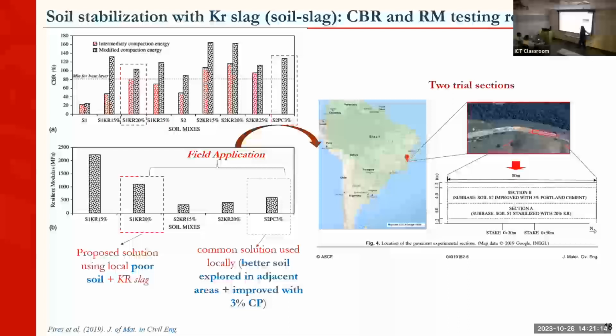We did some mechanical tests. I just put resilient modulus and CBR, and I highlighted the two cases here. The poor soil with 20% slag, and then the better quality soil mixed with 3% of Portland cement. This was the common solution locally in the state where I did this research. They were using this for sub-base layer.